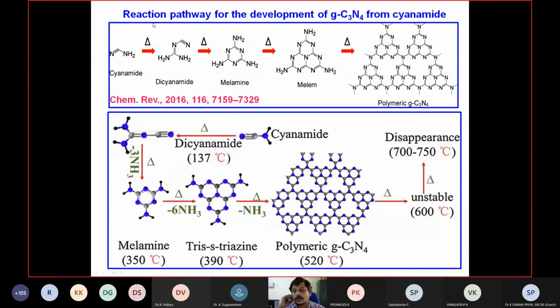Okay, so what is the reaction pathway for the development of graphitic carbon nitride from the molecular precursor, cyanamide? If you take the cyanamide, it will be dimerized, then it forms dicyandiamide, then it will undergo a cyclization reaction, followed by a condensation reaction, it forms melamine, then finally the polymerization process forms polymeric carbon nitride. If you look at this, if you take the cyanamide, then at 130 degrees Celsius, it forms the dicyandiamide by liberating ammonia. Further, if you increase the temperature, it forms melamine. Then further, if you raise the temperature, it forms melon. Then finally it forms polymeric carbon nitride. If you raise the temperature further, it will get fragmented. Then finally the carbon and the nitrogen both will disappear beyond 700 degrees Celsius.